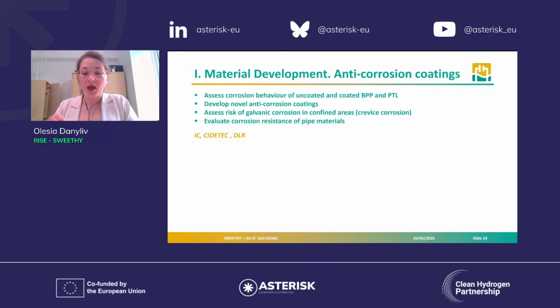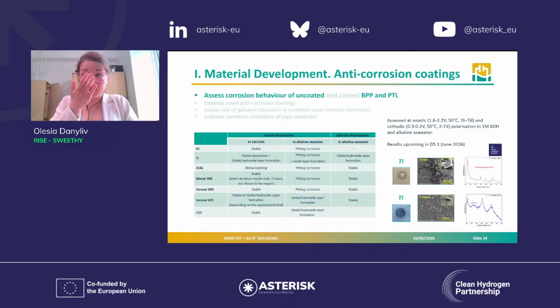of pipe materials. So far, the material that can be found in 10 days time at our website is the deliverable 5.1, which shows, it's a report about corrosion behavior of uncoated metallic materials inside the cell, where we present the behavior of this matrix of materials that you see in front under anodic and cathodic polarization in alkali and in seawater. And here just a few images to increase your attention to this deliverable that is coming up.